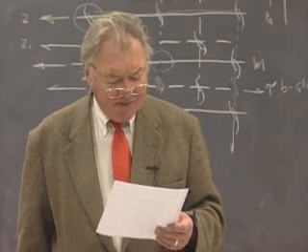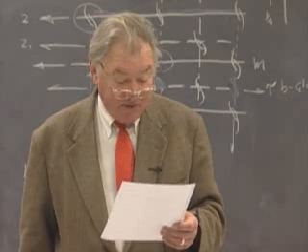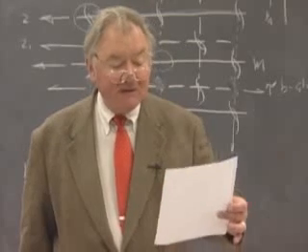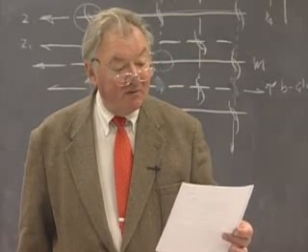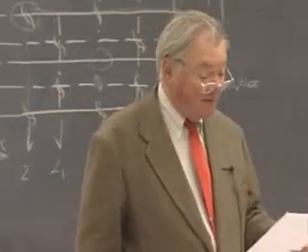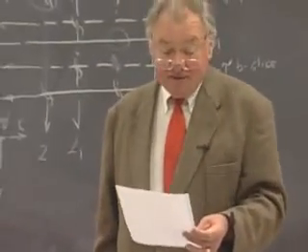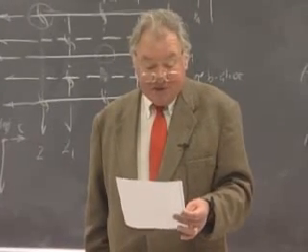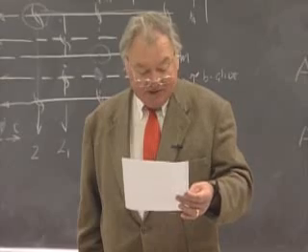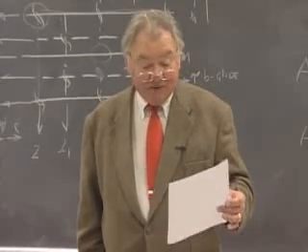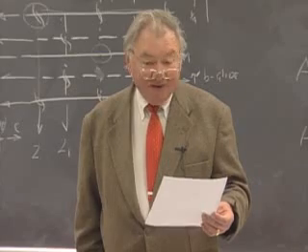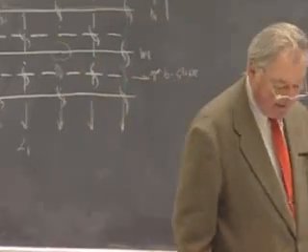Again, because the symmetry is so high, surprisingly, there are not that many special positions, because all of the symmetry elements that can serve as special positions are related by the symmetry that's there. So this is all that you see for the body-centered lattice with 4 over m, 3 bar 2 over m dropped into it. And again, you can describe some very, very complicated crystal structures with a very brief set of notes. Give the value of the single lattice constant A, and then say you've got an atom in the general position, 96L, with x equals something, y equals something, z equals some number, and another atom in position 16F, x, x, x, and just the value of x would be given. So you've described a structure that has roughly 125 atoms in it with just that modest specification of atomic positions.